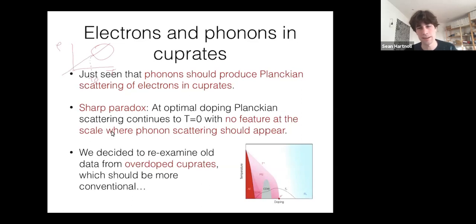And it's very hard to see how phonons can do that, because below the Debye scale, it's much harder to populate phonons. Famously, the resistivity goes like T to the 5th in a conventional metal at low temperatures, not like T, it's much weaker. For a boson, at high temperatures the number of phonons goes like T, but at low temperatures the number of phonons goes like T cubed.